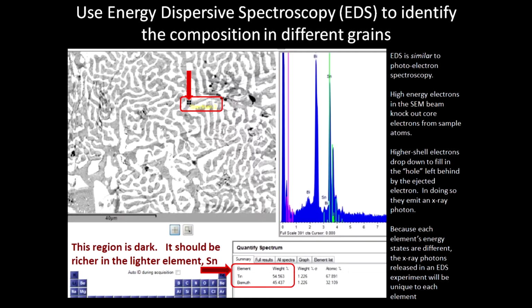Well, all we have to do is capture and measure the energy of that X-ray photon, and that is characteristic of every particular element, right? Every element has its own series of shell energies, and all the jumps in between shells for different elements will be different. And so what you see on the right over here is what's called the EDS spectrum. So the computer has labeled this for us already. I didn't have to identify it. That would be tedious.